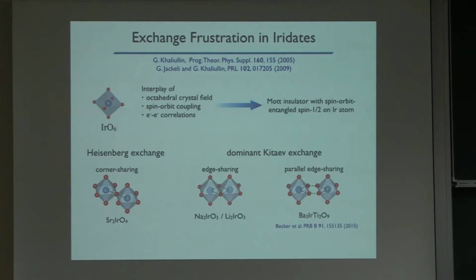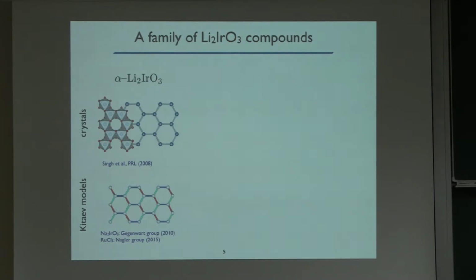really proposed a class of materials. And what they proposed is iridates, both sodium iridate or lithium iridate. And for both these materials, we have now found that indeed Kitaev interactions are the dominant interaction. I'm going to focus on lithium iridate because it's a very interesting compound. So the first iridate compound that was found by the Gegenwart group was what we now call alpha lithium iridate. So the blue atoms, again, these are the magnetic sites, these are the iridiums. You see they form this nice honeycomb structure.